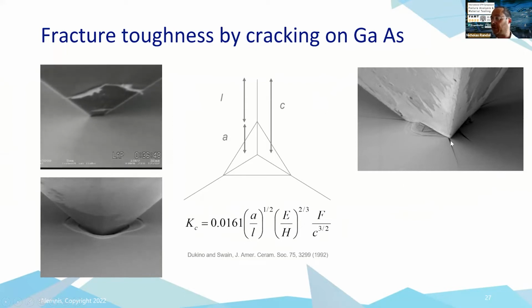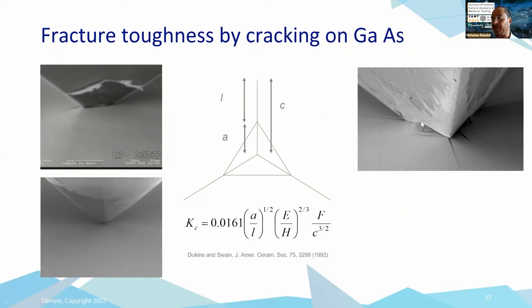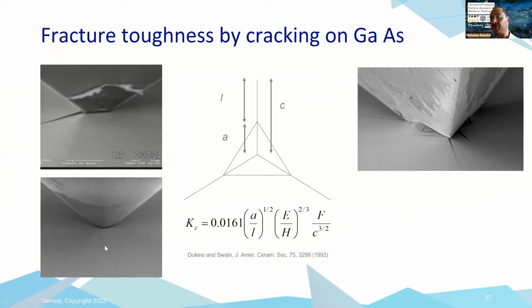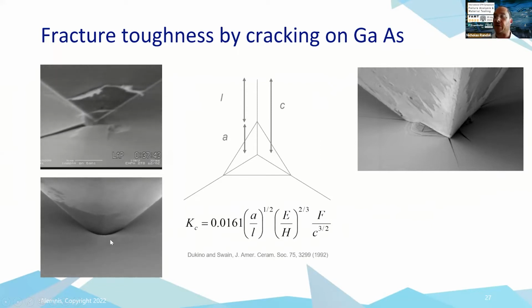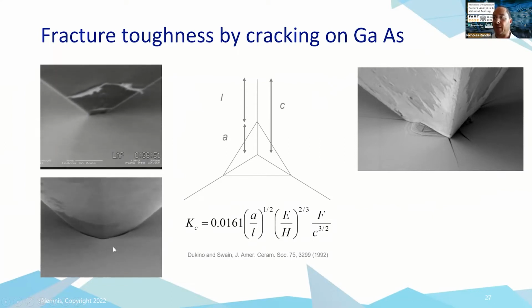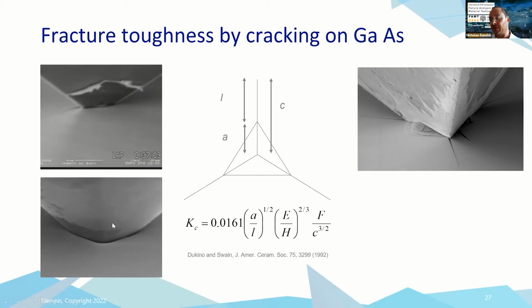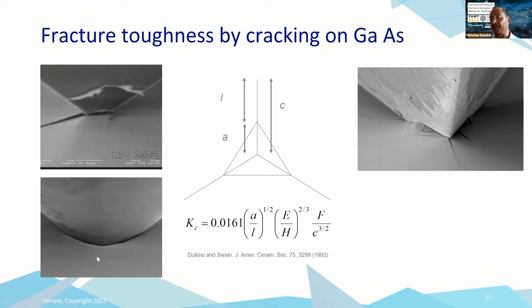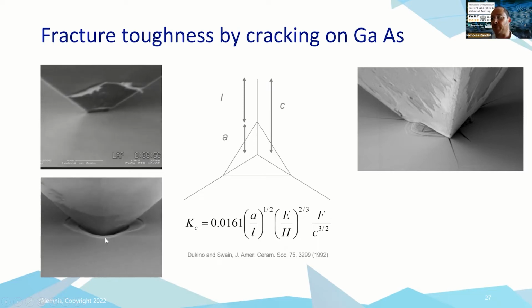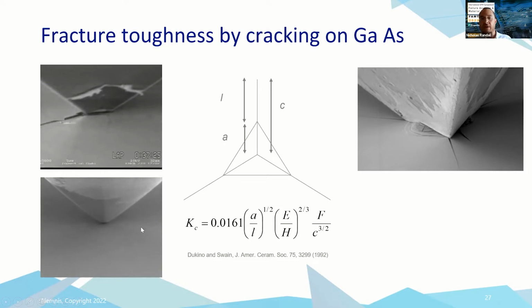And you can see some very nice cracks in this picture on the right, and also a video of some ring cracks being created with a spherical indenter, also in gallium arsenide. So look at this when we unload the indenter here. You can very nicely see those cracks recovering. Here we go. So it's recovering now. We're removing the load. Look at how this bottom part closes up. Look at that. So nice example.